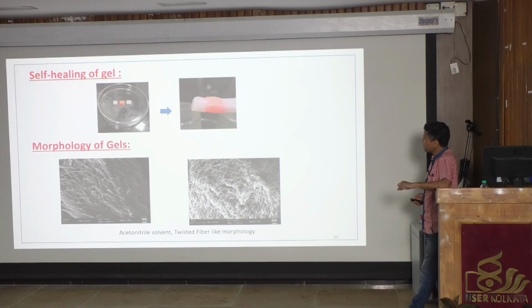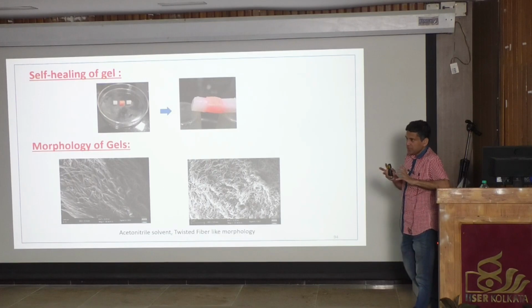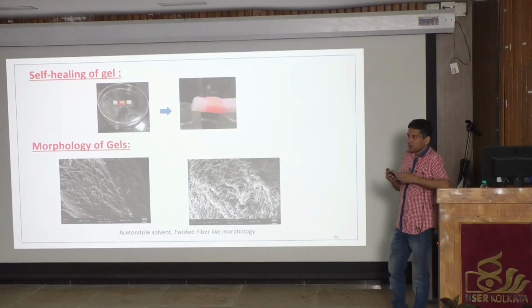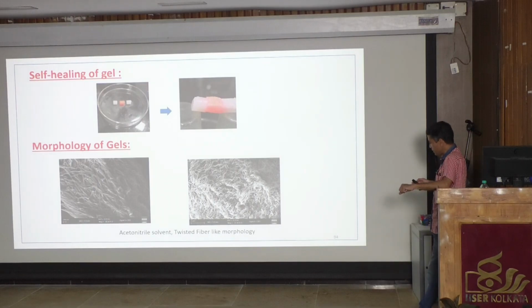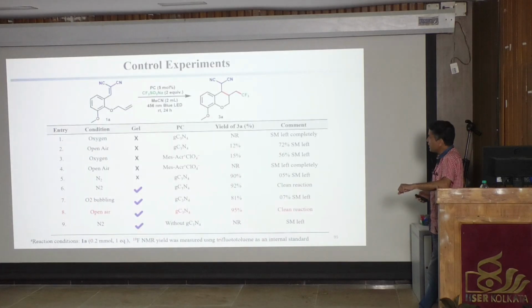The gel is also showing self-healing nature, and this is the morphology of the gel. It's almost like Maggi noodles, very much entangled gel fibers. The confinement is very good. Then we did this reaction with the help of my colleague Suresh Devaraju. So the photocatalyst g-C3N4,